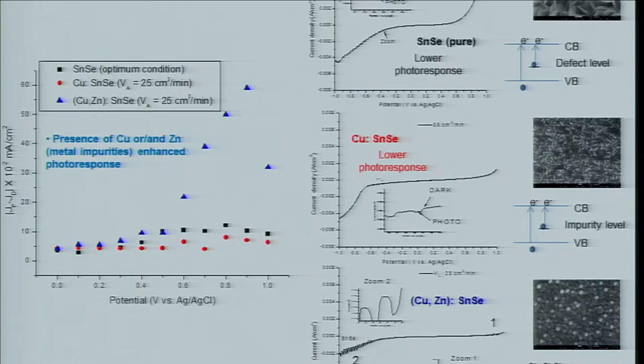And we have proven that using this kind of method, we have obtained a better photo response than the original film. If we just had, let's say, tin selenide, but now we introduce copper or zinc into the tin selenide, it gives much, much better photo response than if it were just tin selenide.